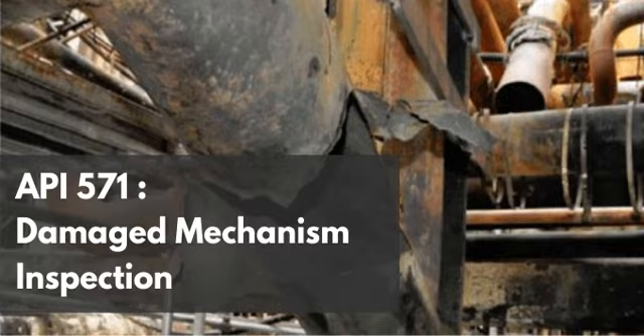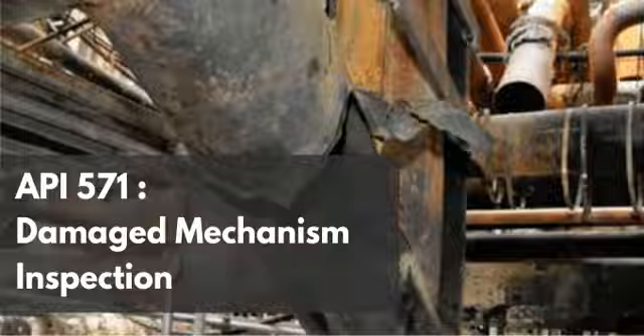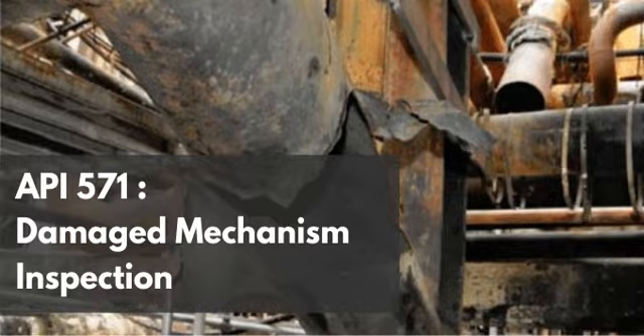And simultaneously, the application of the heat creates temporary massive thermal stresses as the pipe expands. Exactly. You are combining an aggressively accelerated chemical attack with immediate high thermal stress. It's the perfect recipe for instantaneous failure. You basically compress years of stress corrosion cracking into a matter of minutes or hours. The pipe will rapidly unzip itself under the heating bands, or during the steam-out process. That is terrifying. So what's the fix?